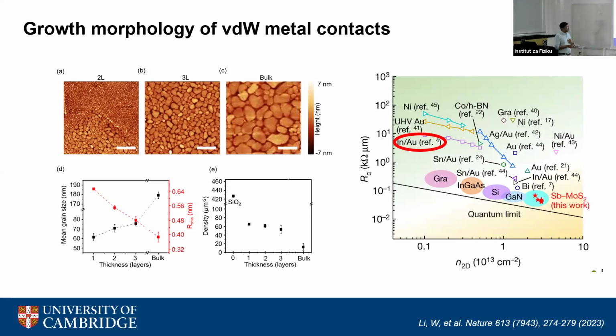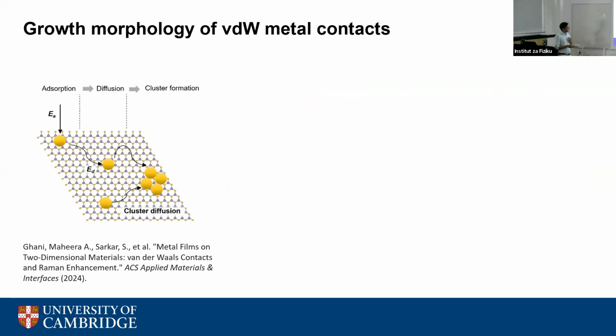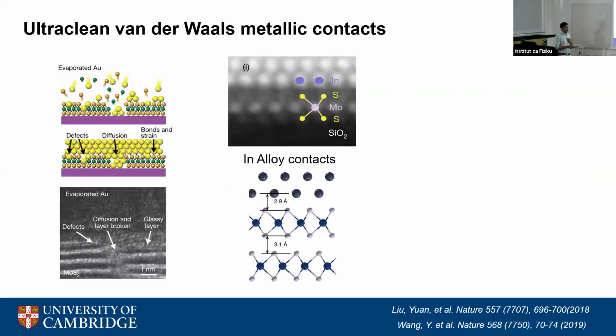So now the community accepts that you need to make van der Waals contacts if you want good devices with 2D materials, because you want to reduce the interaction. But one of the main problems with van der Waals contacts is that you now have a gap between the metal and the semiconductor. Ideally, if you want to improve current, you would want to reduce this gap, because this gap is like a vacuum gap, which is like a tunnel barrier. So this gap acts as an additional resistance for electrons. But if you can somehow reduce this gap and bring them closer to the sulfur, then they will have higher electron injection. But what we want is for them to be very close, but not to damage them.